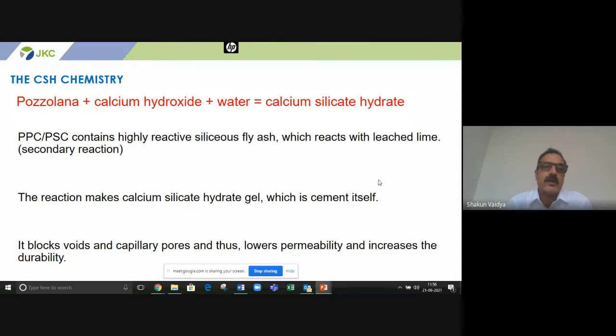So pozzolanic material plus calcium hydroxide plus water gives CSH gel, which further reinforces the concrete and blocks voids and capillary pores, lowers the permeability and increases durability. The challenge is only to lower the permeability of concrete. The finer the pores, the lesser is the probability of moisture or other chemicals reaching the embedded steel.